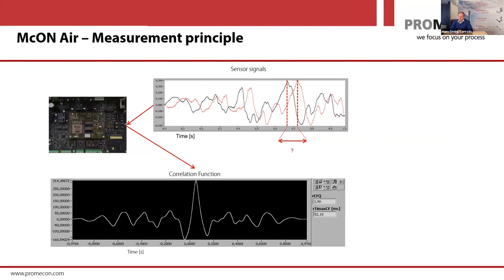Now, why is this so important? It is so important because the only thing that matters in your measurement is the similarity of the two raw signals, which you then calculate statistically. And that means that the only parameter that you are depending on is time. That's it. So it's a pure time measurement. So if you have a time clock on your processor card, you have a repeatability of 10 to the minus 6 or 10 to the minus 7. And that's your repeatability. You will not find any measurement that starts to drift over time.